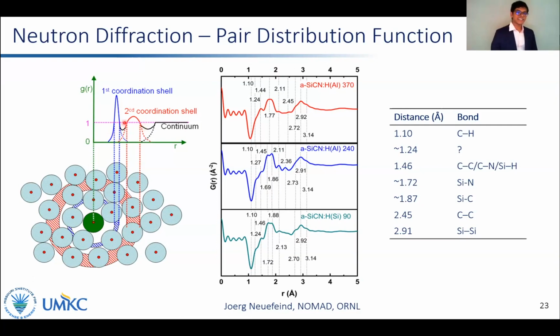And the next nearest neighbor peak corresponds to atoms in the second coordination sphere. This way, we can establish the medium range structure and how various local structural configurations are connected to each other. For our samples, peaks in the 1 to 2 angstrom range correspond to local structure, like single bond distances. For example, peaks at 1.72 and 1.88 are ascribed to Si-N or Si-C bonds. Peaks greater than 2 angstroms correspond to medium range structure, which requires modeling methods for better understanding.